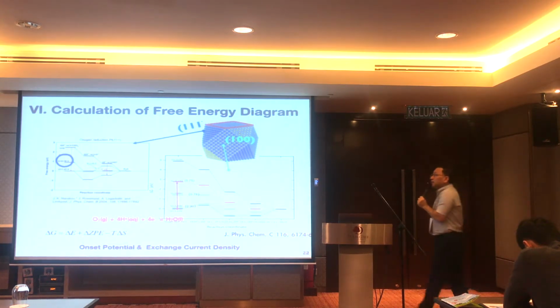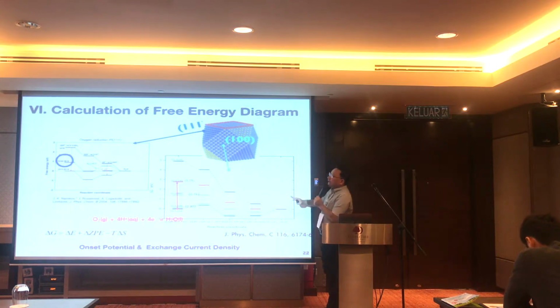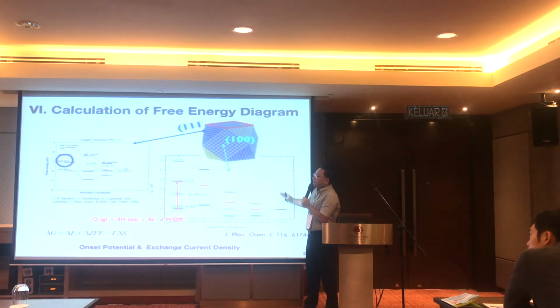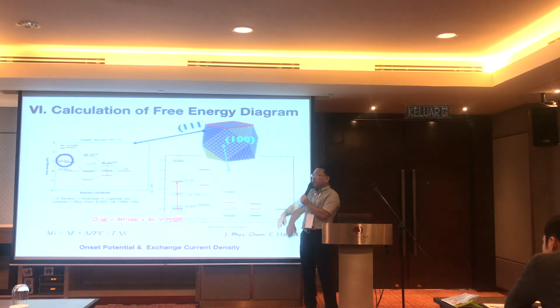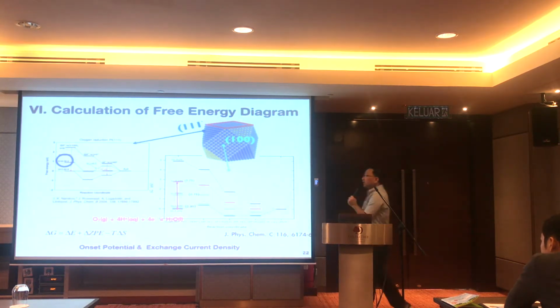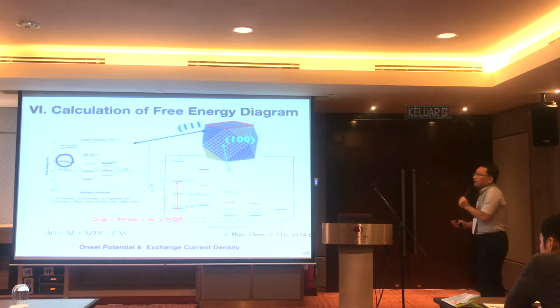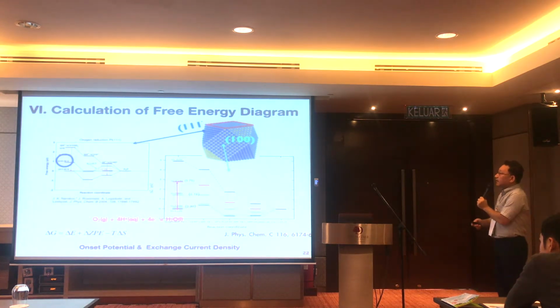What is important is that I can tell the experimenters that you need to save material money, because platinum is very expensive. Only South Africa and Russia are reservoirs. So you need only the 111 surface. You don't need 100, because 100 is very bad in the spontaneity of the reactions. Just use a single crystal, no polycrystals. That's the first principle calculation message we can give to experimentalists.